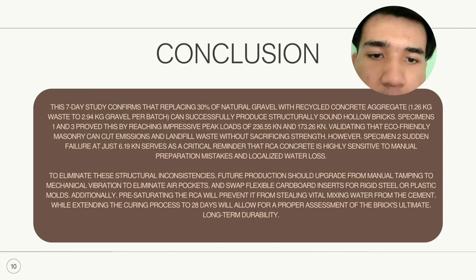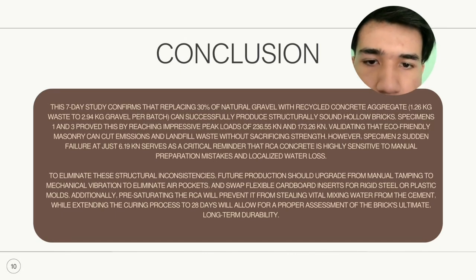However, specimen number 2 had a sudden failure at just 6.19 kilonewtons, serving as a critical reminder that RCA concrete is highly sensitive to manual preparation mistakes and localized water loss. Then to eliminate this structural inconsistency in future production, I think we should upgrade from manual tamping to mechanical vibration to eliminate air pockets and swap flexible cardboard inserts for rigid steel or plastic molds.